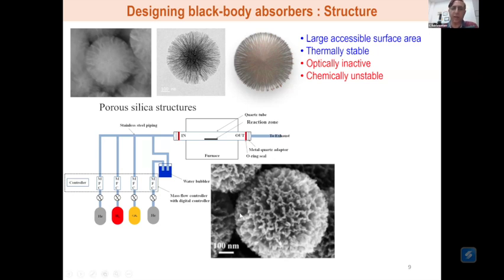Once the entire surface of SiO2 is coated with carbon, all you need to do is take it out and put it in sodium hydroxide. It will react with the silica and etch out all the silica, forming water-soluble sodium silicates. So what is left behind is an integral carbon structure that we have.